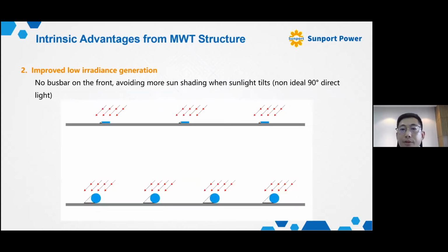Also, when the sun shoots the module at an angle, a typical module will have actual shading caused by the ribbon, especially for those who use the micro BB, the MBB, 12 BB. The ribbon diameter is actually more considerable than the flat ribbon. However, MWT only has fine grid lines and will not have this issue. So the generation at low irradiance will be improved for this reason.